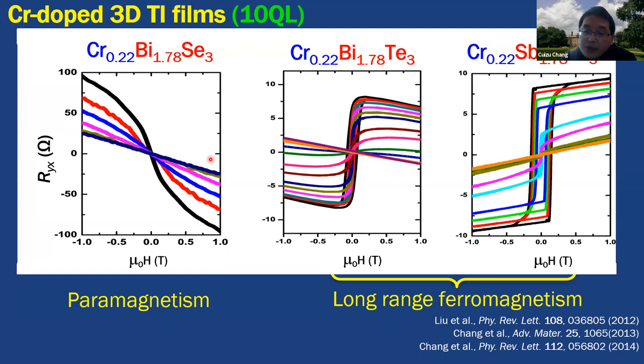And as you know, we use MBE to grow the thin film. And as I just introduced, we need to introduce ferromagnetic order into the topological insulator. So we are using diluted magnetic doping. As you may know, there are three members in the bismuth selenide family topological insulators: bismuth selenide, bismuth telluride, and antimony telluride. So we tried very hard and tried most of the transition metals in the periodic table. So we finally decided to use chromium.